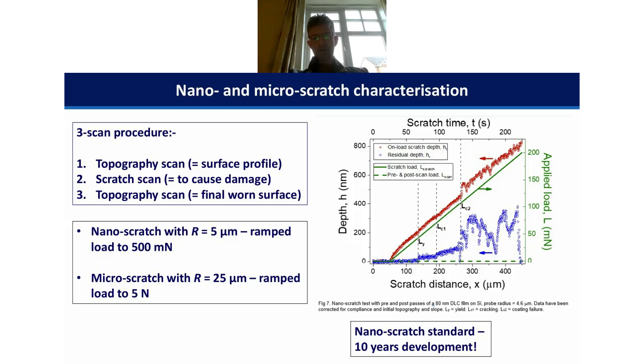So you've heard a little bit from Jan just now about the 3-scan procedure. This is something we developed over a large number of years, and this has recently led to a nano scratch standard that Mark G and myself and others have been working on for a long amount of time, and that's finally been published. In the test that I'm going to describe now, we've looked at nanoscale scratch tests with the low load head with a sharper probe, a 5 micron spherical contact probe, and in the micro range with a blunter 25 micron probe.